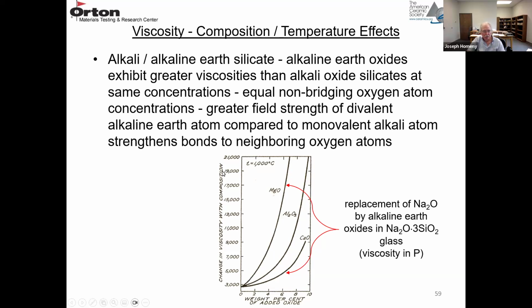So this is the change in viscosity with composition. This is the weight percent oxide. So if we just look at MgO and CaO, they're replacing Na2O, and you're actually having an increase in viscosity because of the greater charge on the alkaline earth ions compared to the alkali ions.